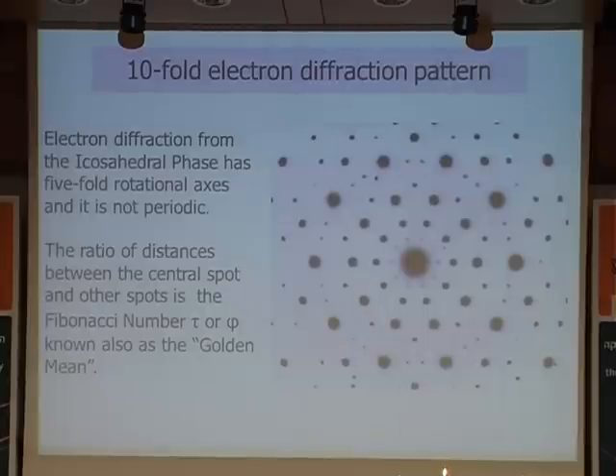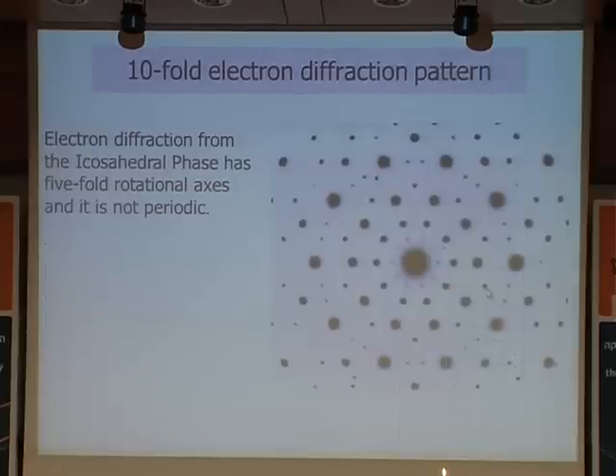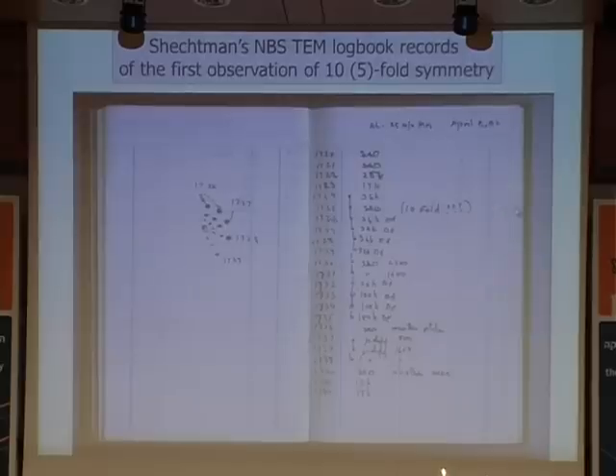And I performed a series of experiments, which you can see in my logbook. Yep. So you can see all these experiments, which are linked by this chain, are done on one crystal. This is a note for me that this is one crystal. And I took a series of dark field images, as I have noted myself here. And the dark field image does the following.